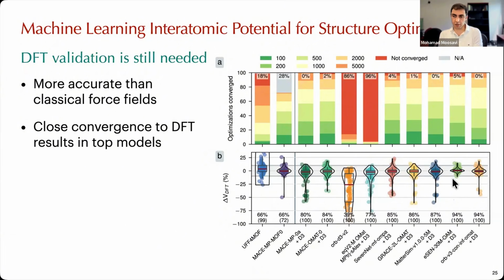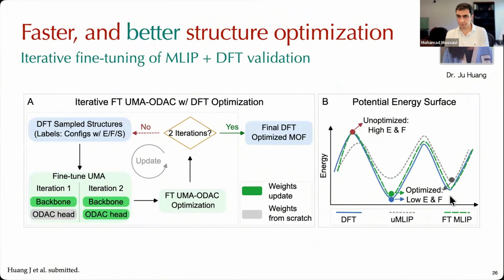But one thing we were not 100% satisfied with was that at the end, it's a bet you make. You are using a machine learning potential, and you are not sure if the final structure that you end up with is valid with DFT, or it might still have some error from the machine learning potential. So that's why I think it is important that we always do the final step of DFT validation to make sure things are converging to the right solution.